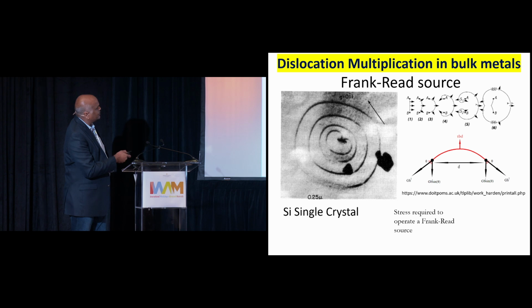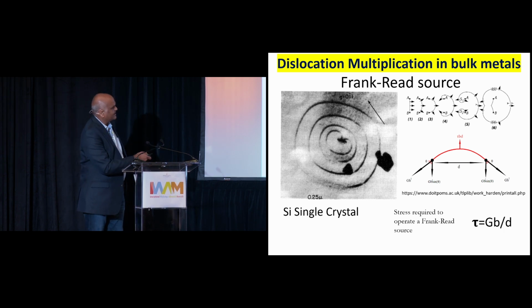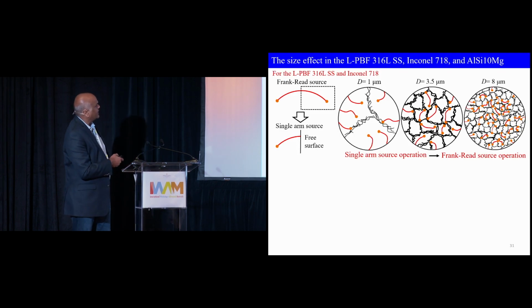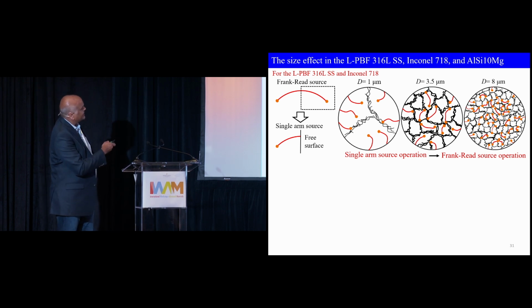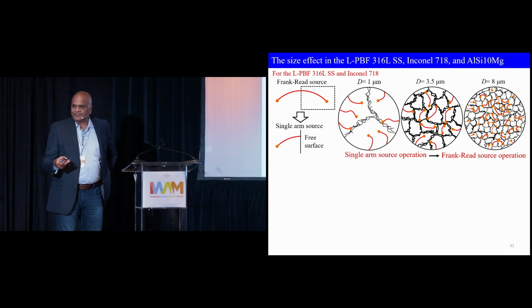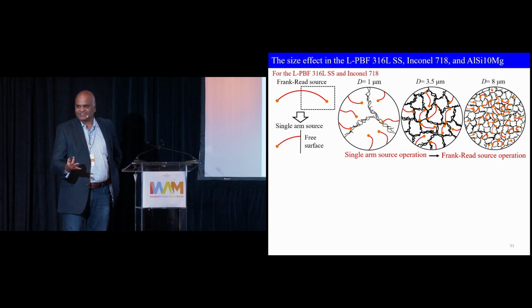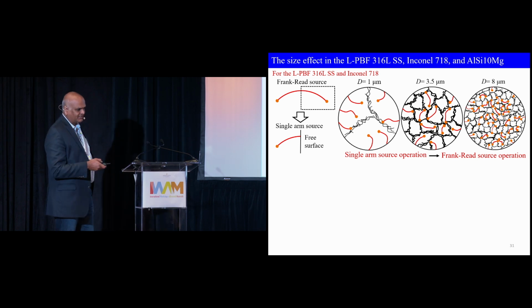The stress required to operate a Frank-Read source inversely scales with the distance, the length of it, GB by D. So what happens when you go to smaller and smaller diameter pillars is that it's not the full length anymore. You have what we call single arm sources, anchored at the surface, as opposed to the Frank-Read source. So when the average length of the Frank-Read source is much smaller, you need to apply higher stress for them to get active, and that's why the yield strength goes up.